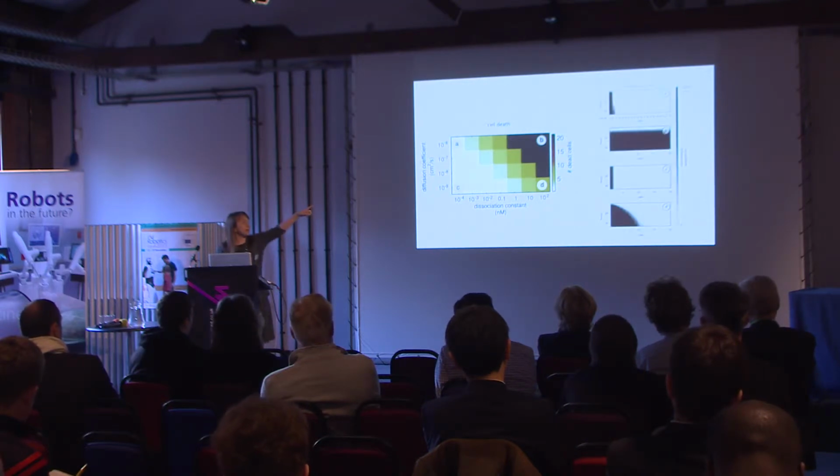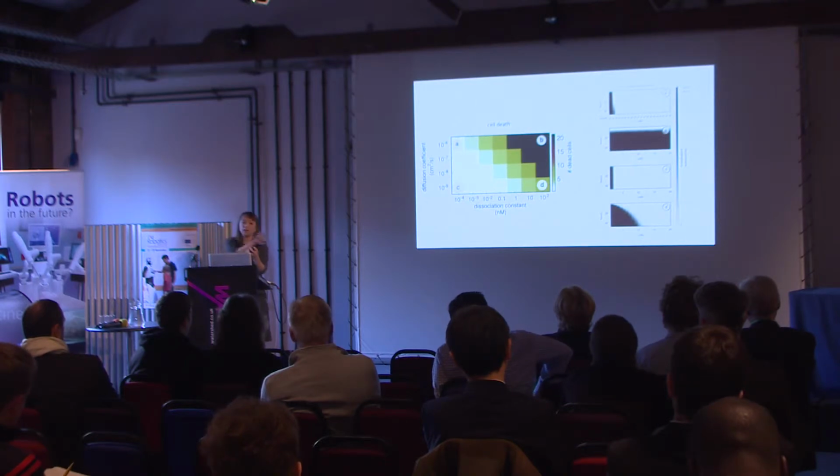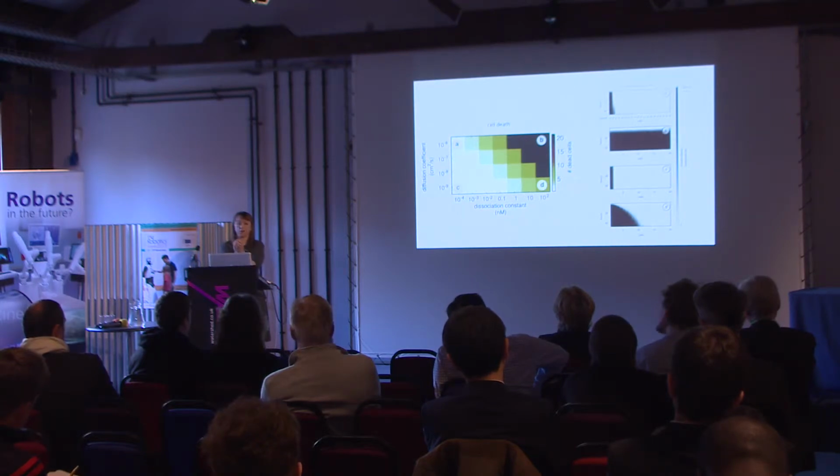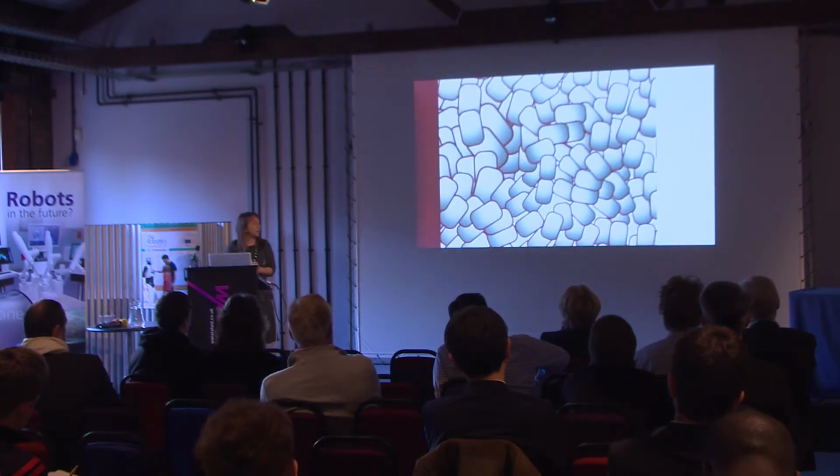So if I take A, for example, A was a particle that was very sticky. What happened is it leaked out of the vessels, and the first cell ate up all the particles. And so they never went deep into the tumor tissue. That was a little counterintuitive for the bioengineers, because when they're designing their particle, they want it to be really sticky, because then it gets eaten up by cancer cells. So it's interesting to think of collectives and dynamics rather than the individuals, and this was a proof of concept. And then you can come up with rules that are easier for them to use.